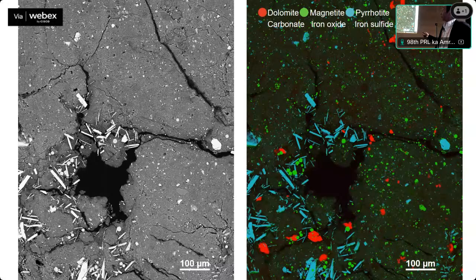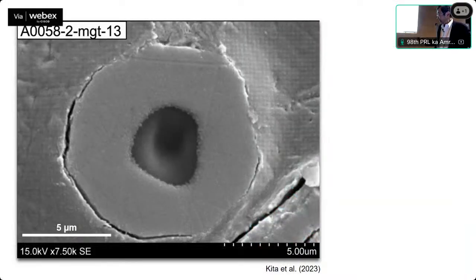The background is clay minerals. This color is pyrrhotite, this color is magnetite, and this is dolomite carbonate. We measure the isotope ratio by using SIMS. SIMS can analyze the isotope ratio from very, very small minerals. Here we measure an area of about 4 micrometers.